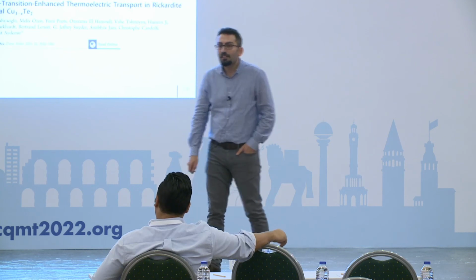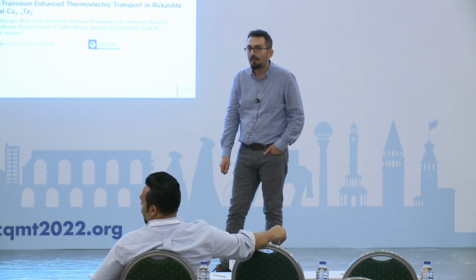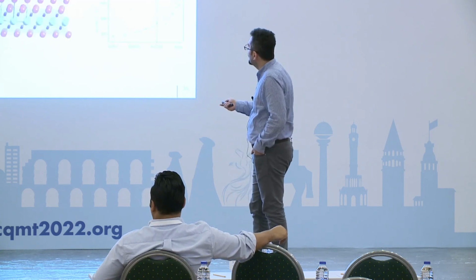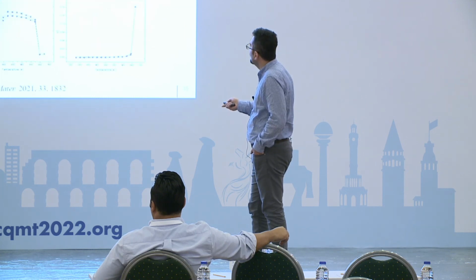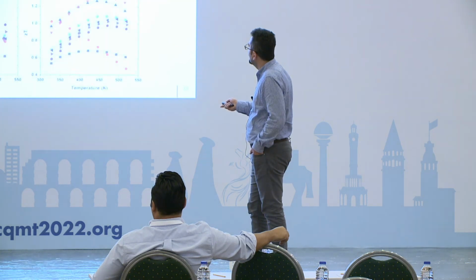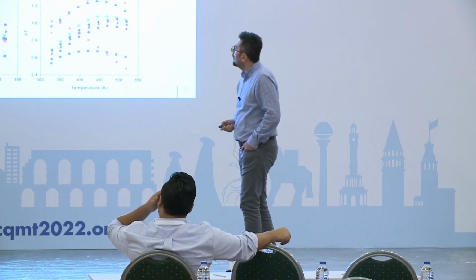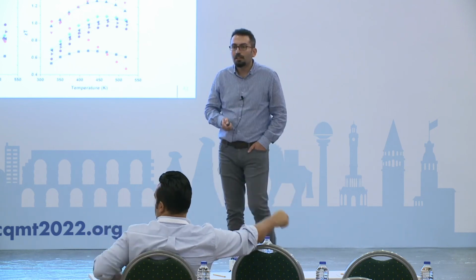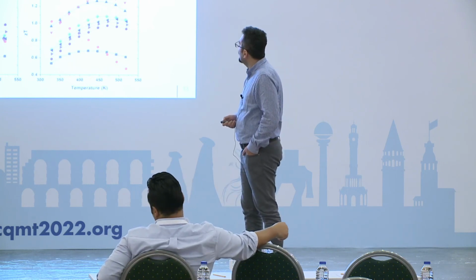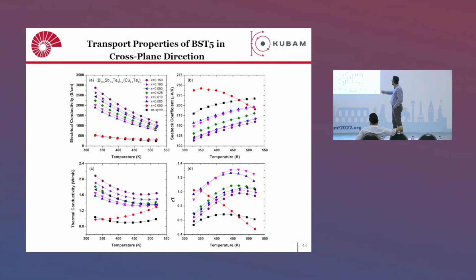Okay, so you had a figure where you showed that with 0% copper telluride, the temperature trend was down in this figure of merit. It's a bit later, I think. Here, yes, you mean? Yes. I have this very simple question. Both figure of merit and Seebeck coefficient have exactly the opposite temperature trend at 0% copper telluride and not 0%. Okay. This one, you mean? Yes. The red one. This one sticks out. So do you have some kind of simple, quick way to understand that? Yes, sure. You mean the Seebeck coefficient, right? This going down of the Seebeck coefficient as opposed to others. Yes. Kind of, yeah. So that is the thing.